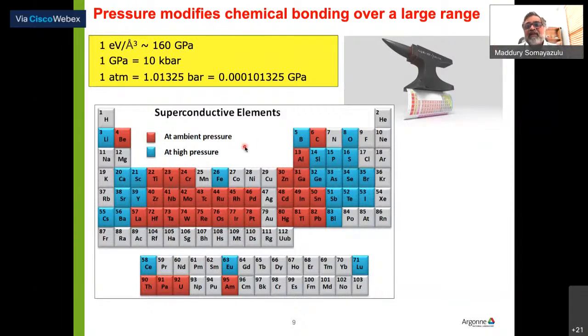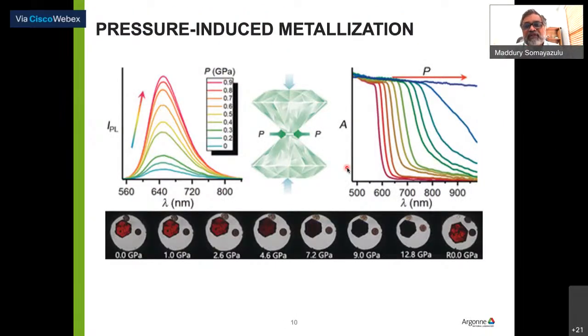So for example, here, since the theme of this talk is superconductivity, let's look at elements. You see that at ambient pressure, all those elements listed in red have a superconducting transition at atmospheric pressure at various temperatures. The minute you start applying pressure, you literally double the number of elements which show superconductivity. In fact, the highest temperature of superconducting elements is in sulfur, which is at a fairly high pressure. So what it tells you is that pressure tunes the bonding and therefore the electronic properties of materials, and therefore makes new possibilities.